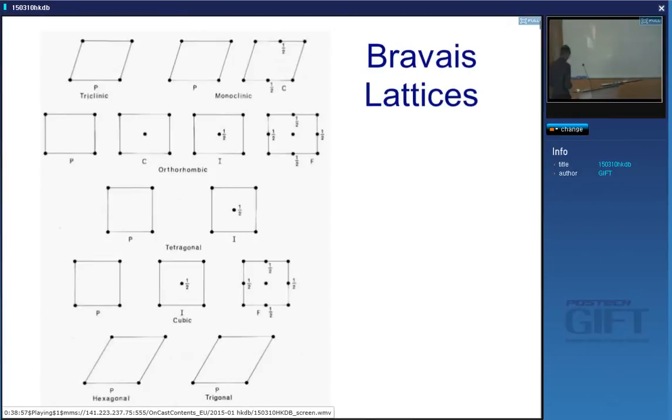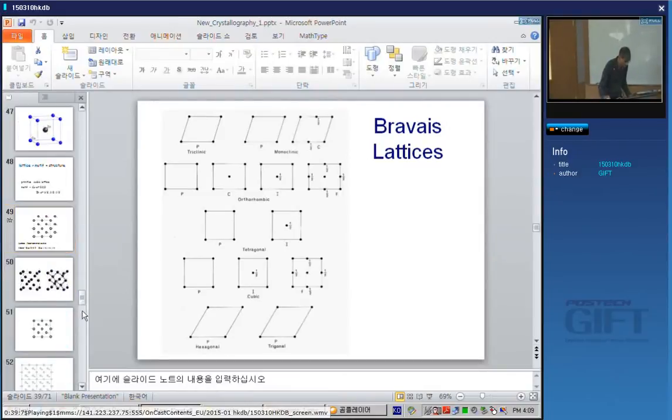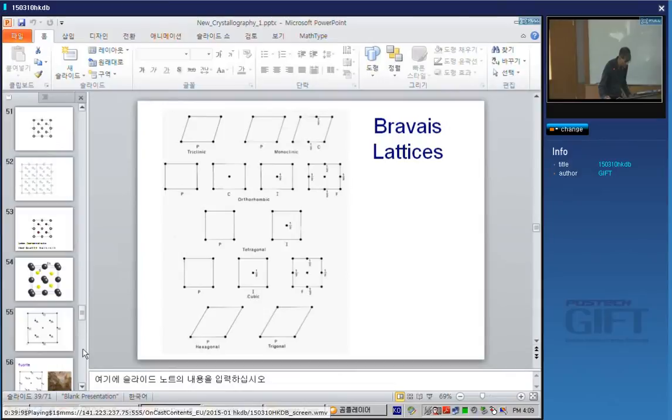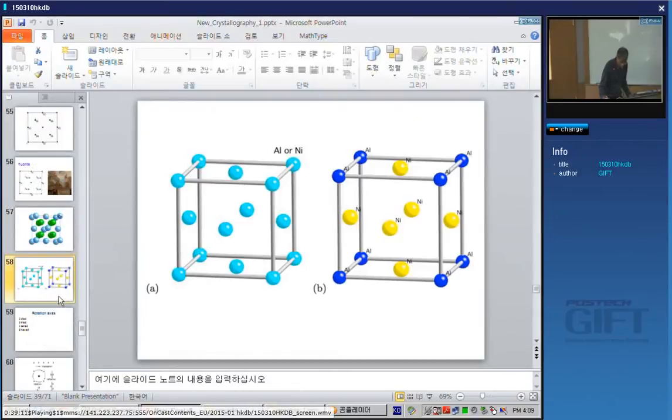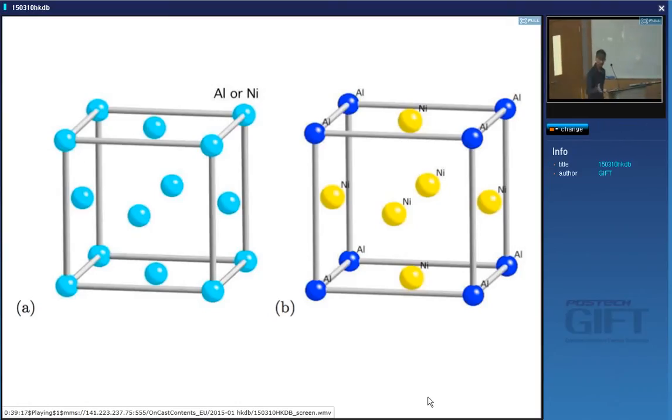So I actually get a 001 reflection. So with this ordered phase, when I do electron diffraction or X-ray diffraction or neutron diffraction, I will get intensity corresponding to the 100 reflections for the ordered phase, but not for the disordered phase. Okay.